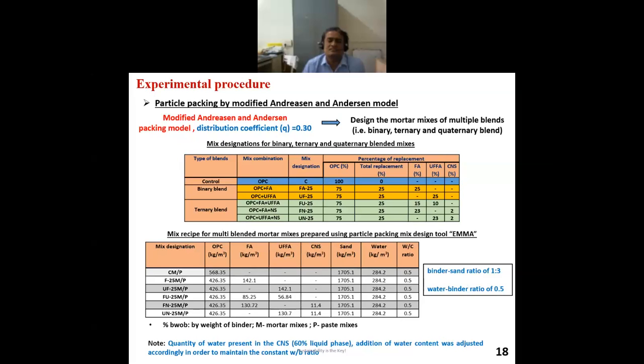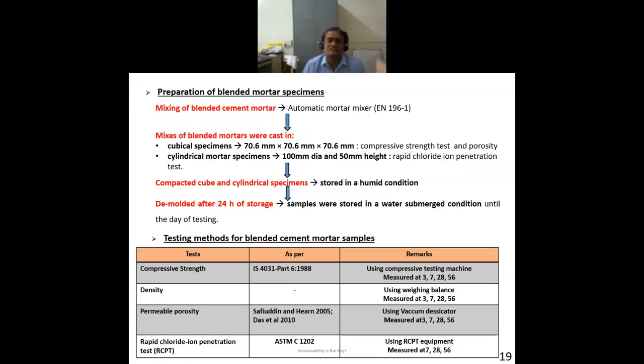Then we actually did the casting in two phases. One is preparation of the blended mortar specimens. This was done with an automatic mortar mixer. That is, the blending was done with an automatic mortar mixer. Then the size, we know, for mortar is 70.6 by 70.6, a cubical mold actually. So compressive strength and porosity were done with the help of these specimens. Then cylindrical specimens, 100 mm diameter and 50 mm height, were made for the rapid chloride ion penetration test, that is the RCPT test.